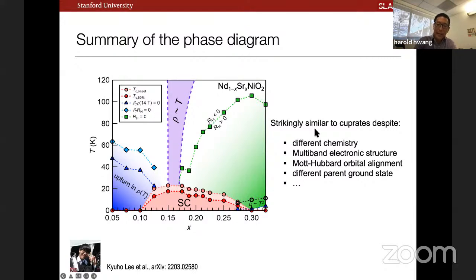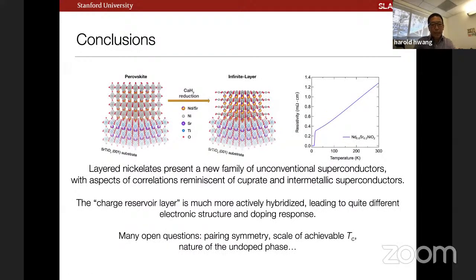Let me simply say that this phenomenology, as we improve the materials quality, is approaching rather closely that of the cuprates. And this is despite some significant differences in the chemistry, in this intrinsically multi-band or self-doped electronic structure, in terms of being more in the Mott-Hubbard regime versus the charge transfer regime in the cuprate problem, and of course, this fundamentally different parent ground state. So yeah, let me conclude there.